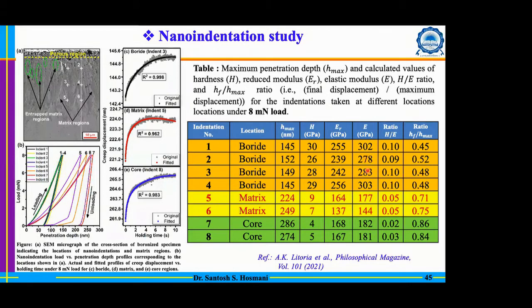Now the question arises: if the material is very stiff, there is a possibility of cracking during growth. Fortunately, if you look at another column here, that is H by E. This H by E gives us information about the elastic strain. Even the HF by H max is linked with that. And you can see here that the elastic strain, the H by E ratio, is very high compared to the matrix and even compared to the core.